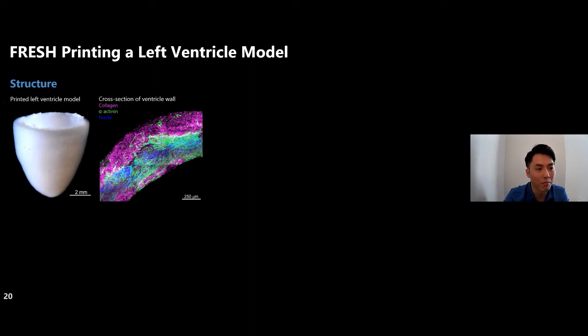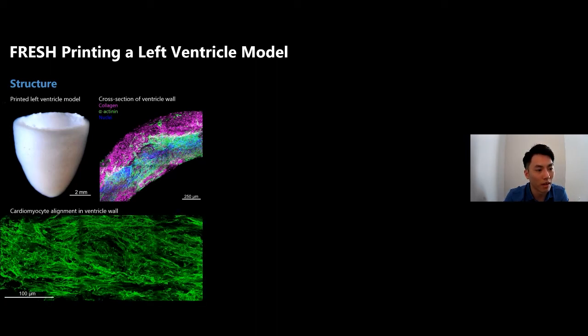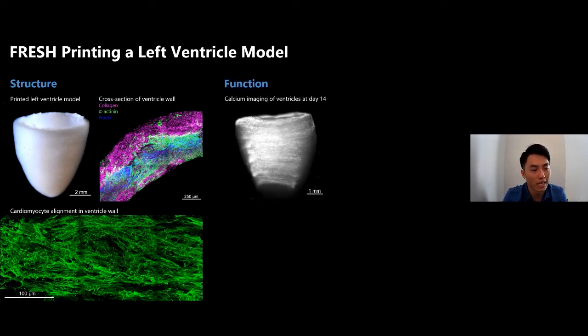You can see in green and blue, with magenta showing collagen. And when we take a closer look at these cells, we find that they not only have been printed, they also remain highly viable, aligned to the direction of printing, and also elongated and well connected in a dense network. When we then study the function of our printed ventricle using calcium imaging to observe the electrical activity of these cells, we find that the calcium wave propagates throughout the entire surface of the ventricle that we printed, and it's a homogeneous propagation across the surface.